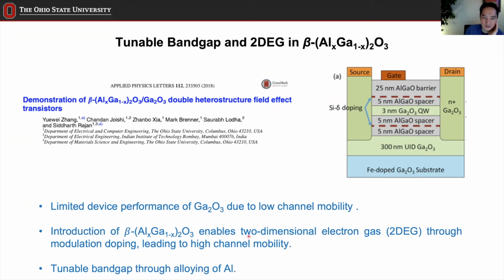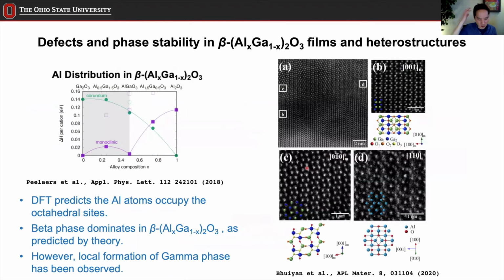The other thing is that aluminum oxide is almost an insulator, so it has a very large band gap. By introducing aluminum, you can tune the band gap, which can actually be larger. There's a potential to also tune the breakdown voltage and everything. And apparently making aluminum gallium oxide is easier than aluminum gallium nitride, meaning it's very promising. The defect level is very low when you do this type of alloying, so it's a very promising method that has been studied extensively for the last couple of years. That's what our device collaborators are doing.